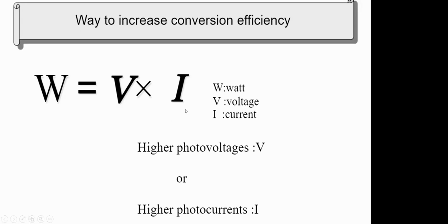By introducing a better absorber, which absorbs more incident photons. More incident photons will generate more current. But how can we include a higher operating voltage? In that case, we need to integrate a very high conduction band electron transport material, and then the respective quantum dots' or dyes' conduction band should be above that but close to it.